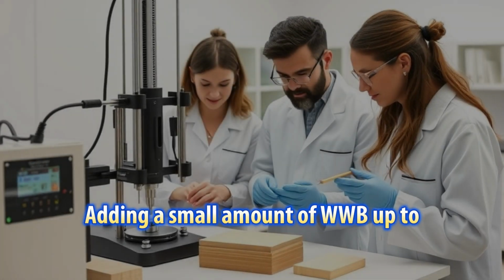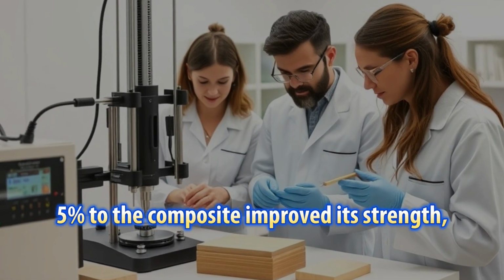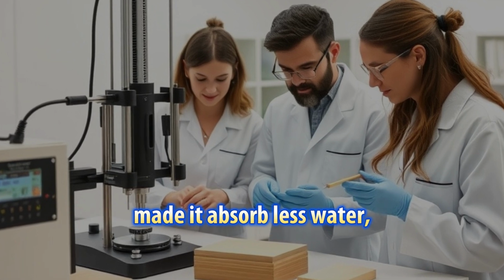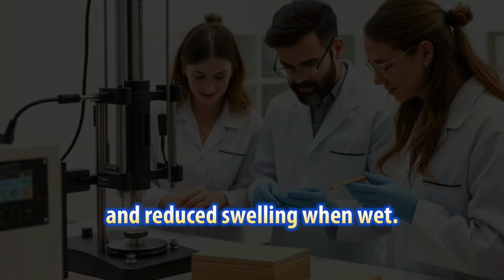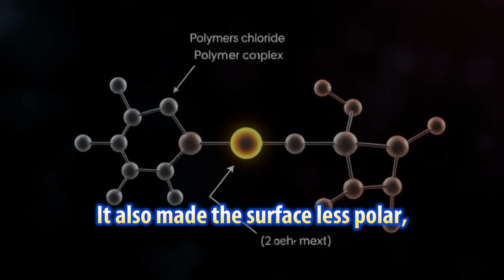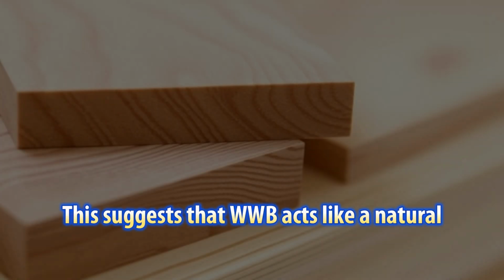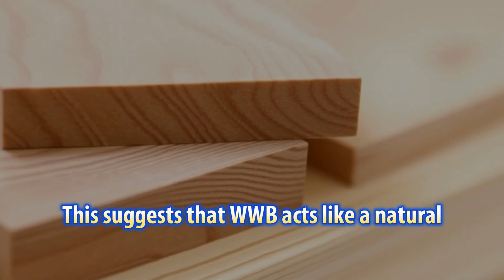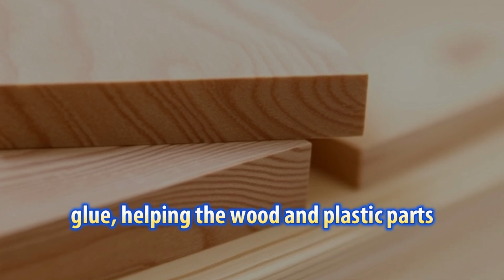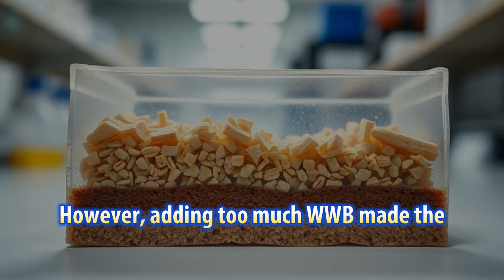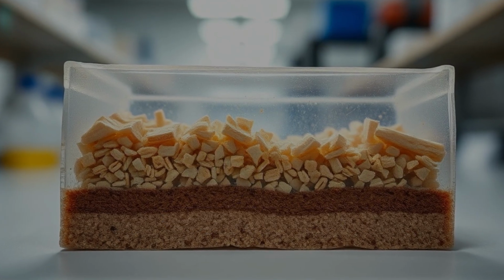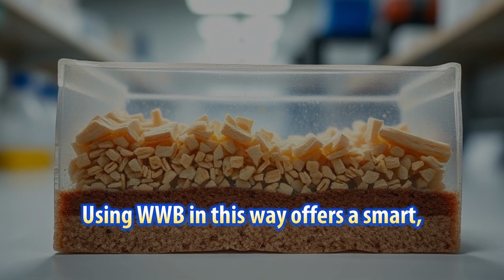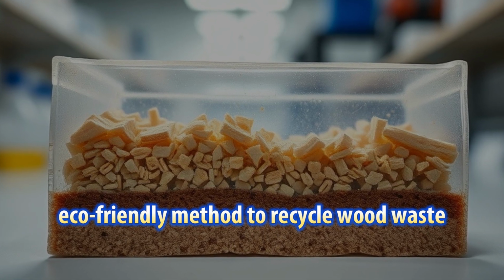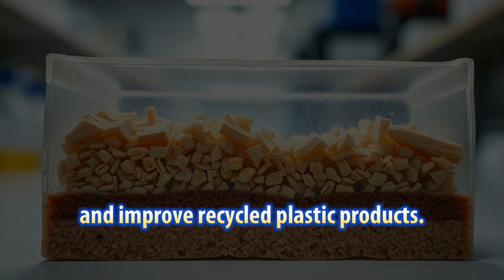Adding a small amount of WWB, up to 5%, to the composite improved its strength, made it absorb less water, and reduced swelling when wet. It also made the surface less polar, which helps the materials stick better together. This suggests that WWB acts like a natural glue, helping the wood and plastic parts bond well. However, adding too much WWB made the composite weaker. Using WWB in this way offers a smart, eco-friendly method to recycle wood waste and improve recycled plastic products.